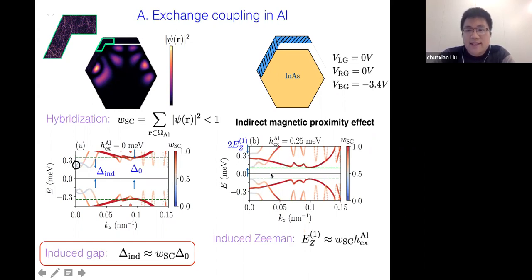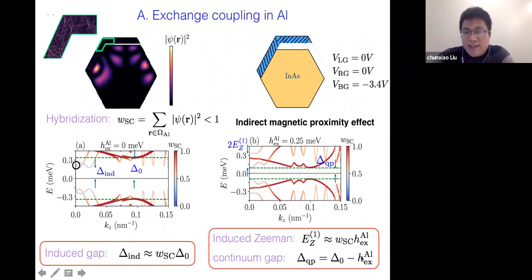And the second observation here is that the gap of the superconducting state is reduced when the exchange coupling in the aluminum is finite. And the reduction is almost linear, which is the typical property for an s-wave superconductor in the presence of a Zeeman energy. So one question we ask now is, if this exchange coupling inside aluminum is the only source for inducing Zeeman energy in the system, is it possible to realize topological superconductor in this hybrid nanowire?